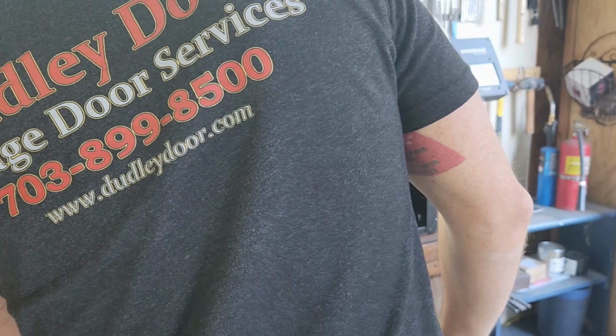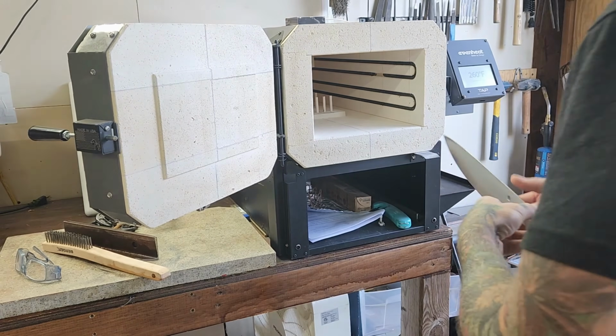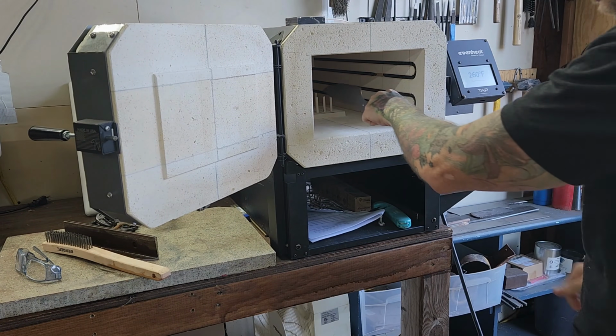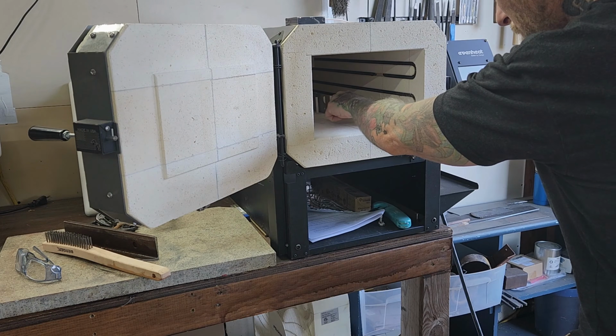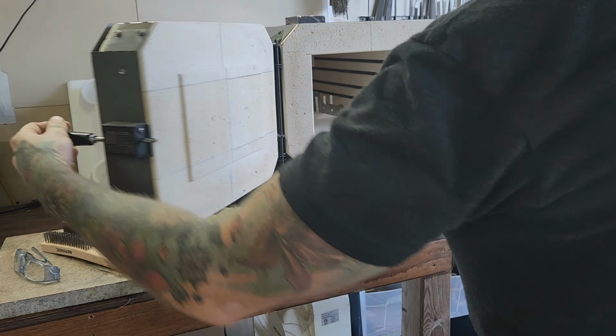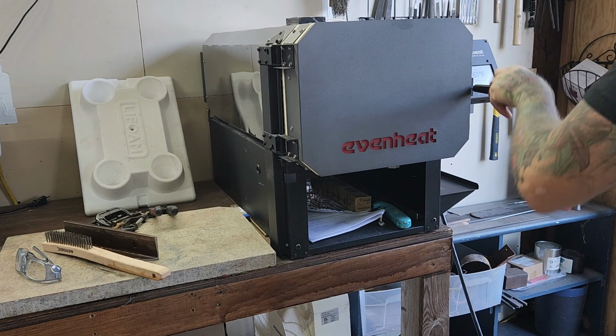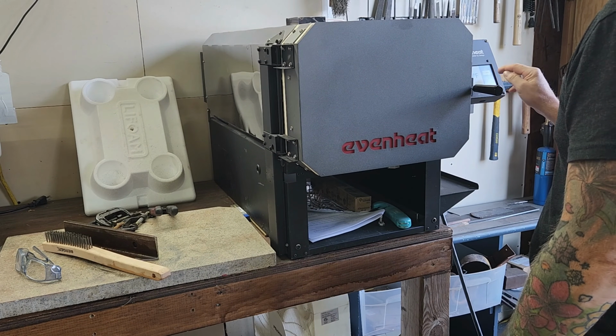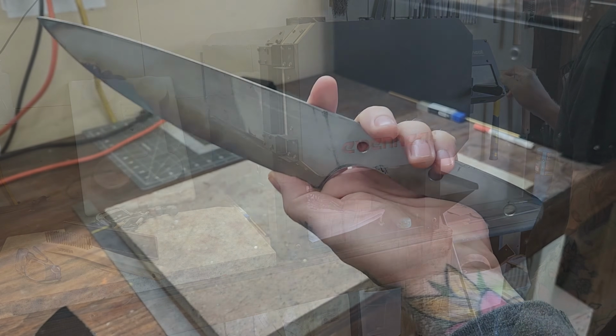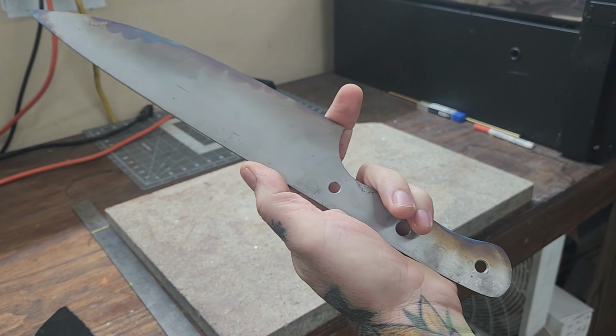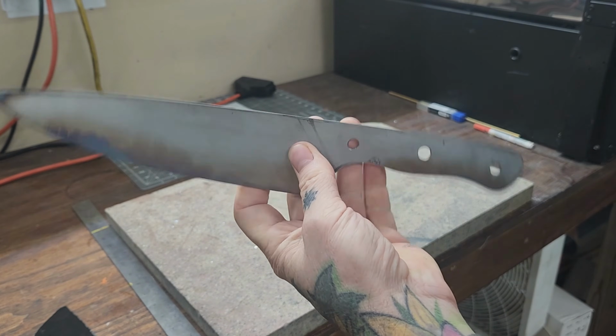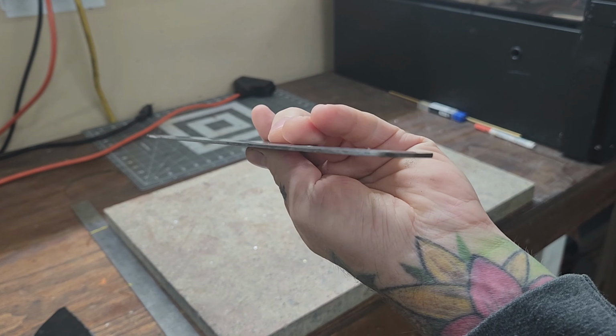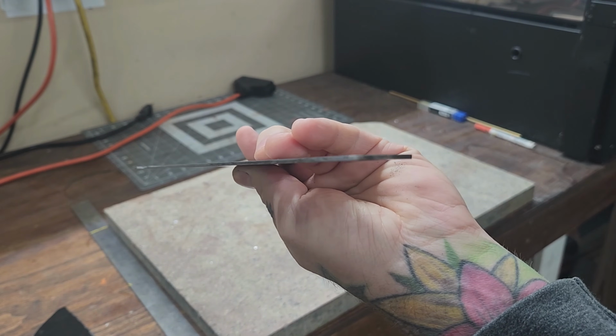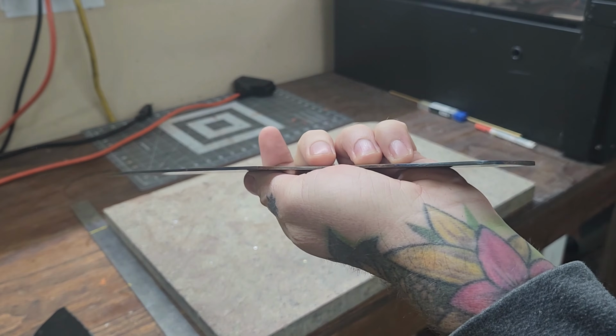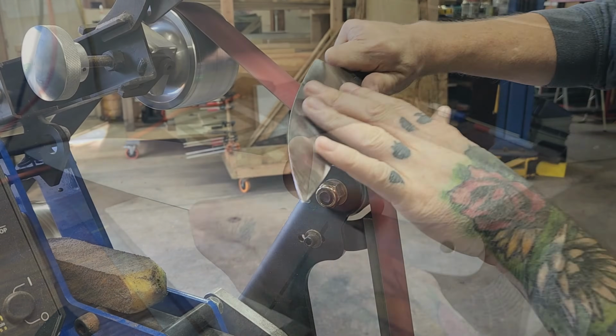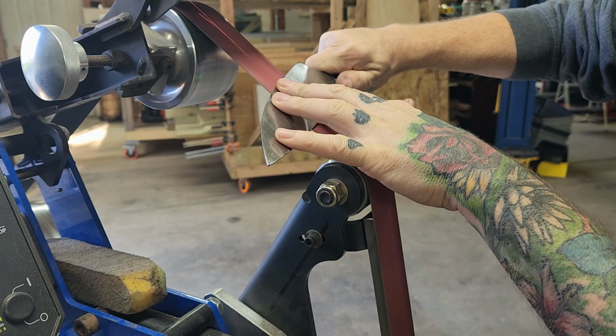The last step in the heat treating process is the tempering cycles, and with this blade I put it in the oven at 400 degrees and let it sit for 2 hours. Then I shut the oven off and open the door about halfway so that it cools down kind of quickly, but not as quickly as it would if I pulled it out in the open environment. And once it reaches ambient temperature, I put it back in and do the same thing again, 400 for 2 hours. And then I open the door again and let it cool back down to room temperature. And we've got a heat-treated blade here with no warps or anything. Looks really good. And we start the grueling process of laying in our bevels and then on into finish sanding.